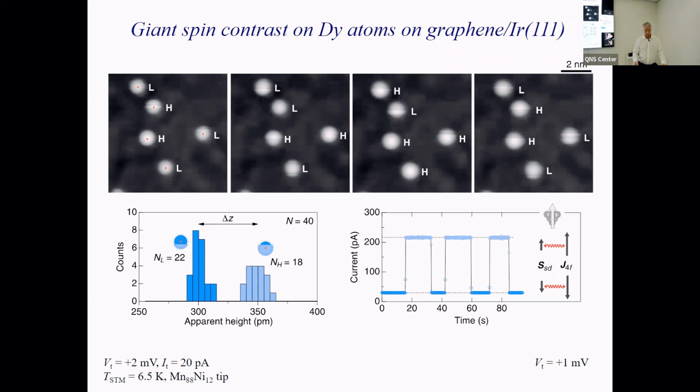And the other point is if you want to make them more stable, one has to look for systems that don't start to diffuse. So these are atoms that have a magnetic stability up to 30 and something Kelvin, maybe 35, 40 Kelvin roughly. Even this dysprosium can potentially be stable up to 30 Kelvin, I can imagine. But at 50 or 60 Kelvin or so, they will start to diffuse. So if they are sitting on a surface, they will start to diffuse at some point. If you want to go to higher temperatures, one has to embed them into surfaces, but then they lose their interesting properties in many cases, because then they would form bonds to the neighbors in the surface where they are embedded.